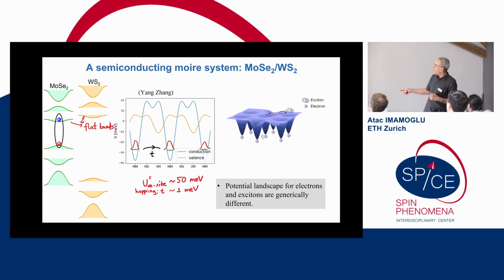Again, this is the structure. This is a sketch of how the moire flat bands should be. This is a calculation for the conduction band and the valence band, DFT calculations from Yang Zhang. The main message here is that the conduction band has very deep potentials. Depth is about 50, 60 milli-electron volts. Actually, the on-site interaction, this is a conservative number, should be even larger than 100 milli-electron volts. The Wannier orbital size is about 2 nanometers, and this is the regime we're going to consider. We're going to inject electrons and see how the optical spectrum changes.